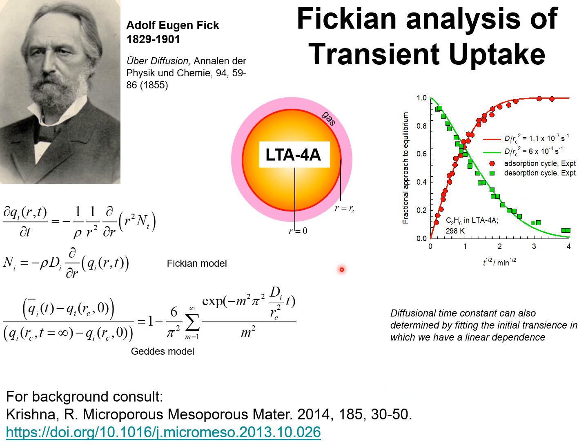Put another way, there is an asymmetry in the adsorption and desorption kinetics. The adsorption kinetics appears to be faster by about a factor 2 as compared to the desorption kinetics. So let us examine the reasons why the asymmetry occurs.